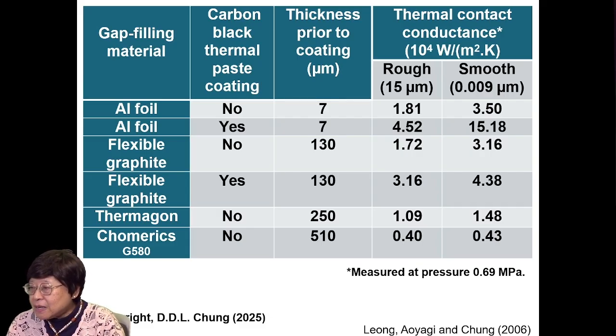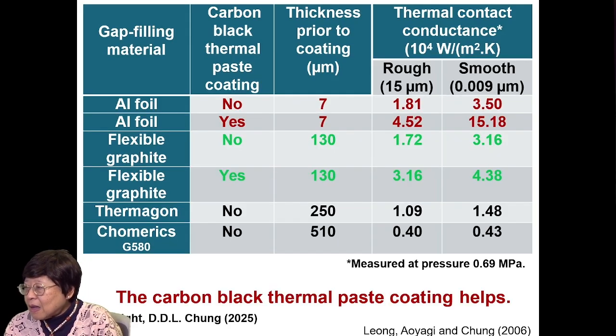Shown here are various gap-filling materials, comparing with and without carbon black thermal paste coating, and also comparing with two commercial gap-filling materials at the bottom. The thickness is indicated. Thermal contact conductance for rough and smooth surfaces are also indicated. And the pressure is held fixed, and the surfaces are copper fixed. And shown here, the carbon black thermal paste coating helps for the aluminum foil. For the flexible graphite, the coating also helps.